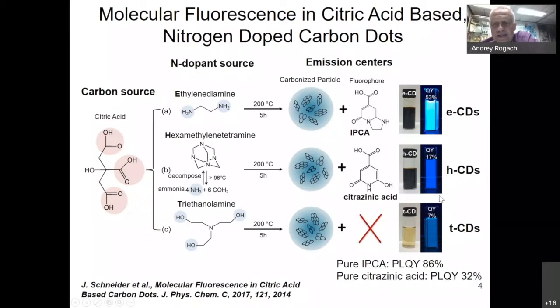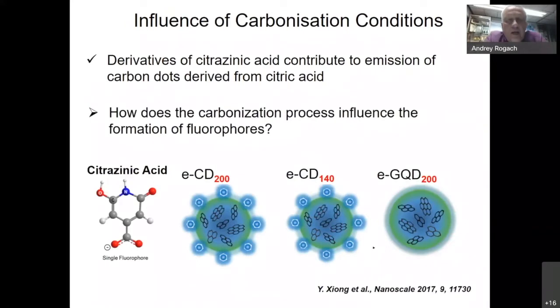So it tells us that these carbon dots, which are formed here only, are still emitting blue light, but their photoluminescence quantum yield is not very high. In 2 other cases, it is higher, and this was actually ascribed to the formation of molecular fluorophores. And of course, carbonization conditions here play a big role. This is something we studied in another study, which was reported here.